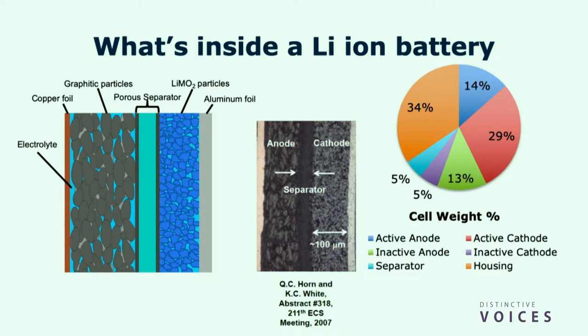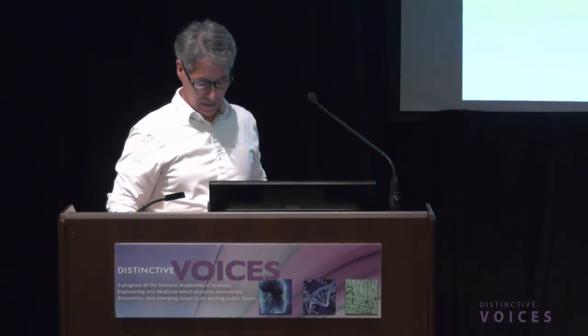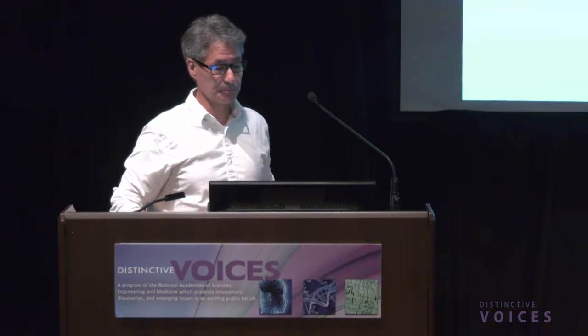But there's a lot of inactive mass with lithium-ion batteries, such as the casing. There's the separator material. For the anode, we can't get away from this copper. It's like 8 grams per cc. It's heavy, but for electrochemical reasons, we have to use copper foil. And so a lot of inactive mass comes from the copper. And then the cathode has the aluminum current collector, and then you have to add carbon to the cathode to make it more conductive. So this gives you an idea of the distribution between active and inactive. And the goal here is to maximize the active per unit mass or volume. So these are the engineering challenges that lithium-ion manufacturers are currently working on.